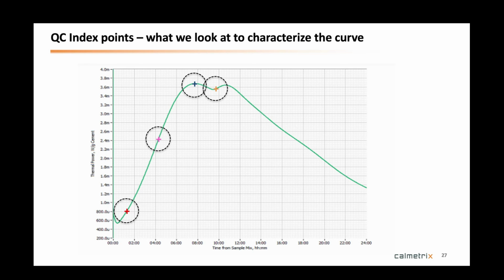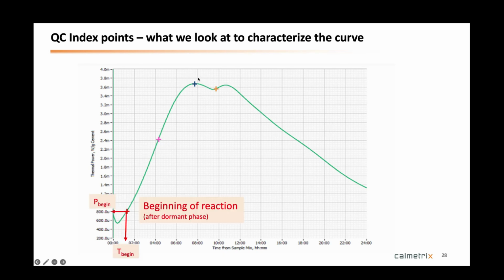So here we have a typical cement curve. It's a Portland cement curve over the first 24 hours. And the first thing we look at is where the reaction actually starts, where it begins. And this is a particular point. We actually have a definition for it. It's the intersection of the tangent that comes from the inflection point where it intersects with the lowest power. But that's a lot of jargon. What it represents is where the reaction takes off after the dormant phase.